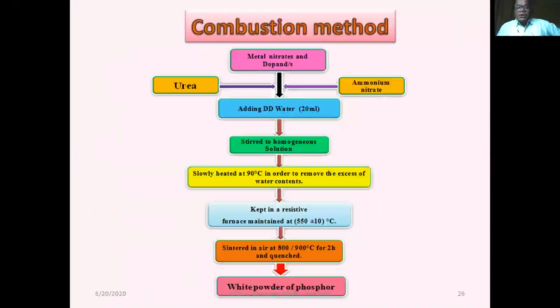In combustion, we usually use urea and ammonium nitrate as fuel and oxidizer, with metal nitrates as starting precursors and dopants. Adding 20 ml distilled water, stirring to a homogeneous solution, slowly heated at 90 degrees centigrade in order to remove the excess water, and then kept in a resistive furnace preheated at 500 degrees centigrade plus minus 10 degrees centigrade, then sintered in air at 800 to 900 degrees for 2 hours, and quenched. Then white powder.